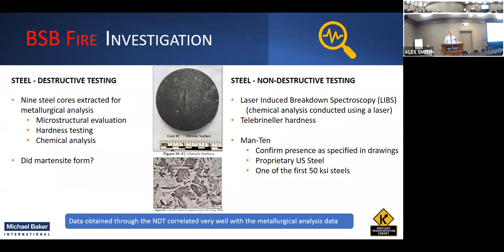Josh mentioned the formation of martensite. Normally within steel construction and steel manufacturing, we can quench steel, which makes it harder, but then we temper the steel, which provides additional ductility. If you only quench steel without the tempering, then you have a much more brittle end result. During the fire event, the yield strength drops, and post-fire that strength will come back, but you may or may not have the same amount of ductility, same material properties. And then there'd be an additional long-term risk to the structure with that.